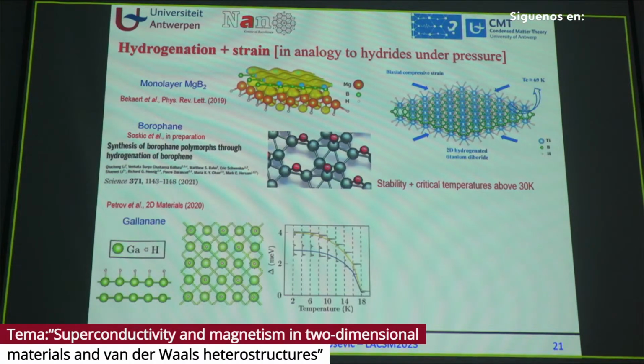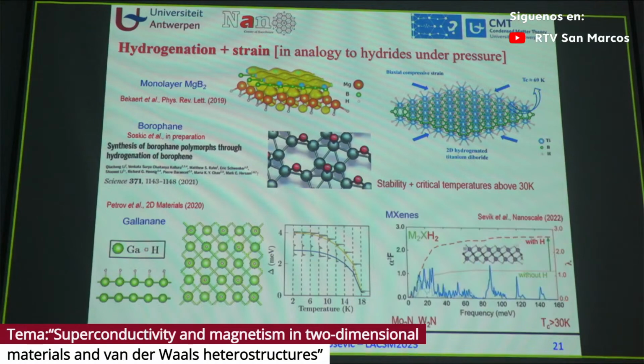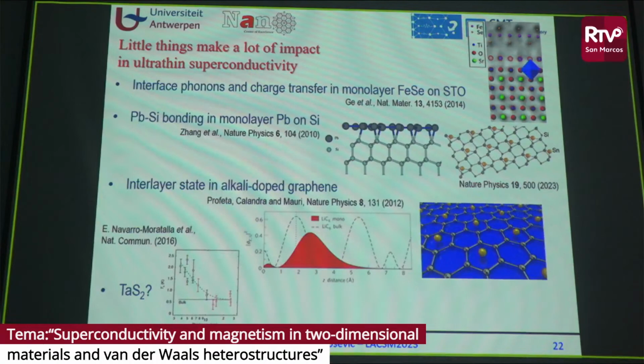Gallanane, so a gallium monolayer with hydrogen, is also superconducting with a respectable critical temperature of 18 Kelvin. And there's a whole family of MXenes that are, of course, a very hot topic in the community for many functional properties. Well, superconductivity is also one of them. In hydrogenation especially, these materials then reach a respectable critical temperature above 30 Kelvin. Okay, now this just goes to show you that small things make a lot of impact in ultra-thin superconductivity.